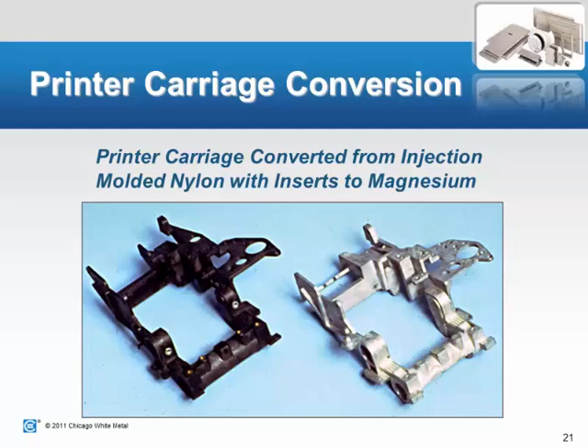This next component was a printer carriage component that started out as a plastic piece with some threaded inserts that were molded in. The customer indicated that the overall strength of the part was not exactly what they needed, but they didn't want to sacrifice very much weight in the overall product by converting to something. So magnesium was a great choice for this. It gave them the strength they need. The weight did not change that much. They could remove all the different brass and steel little inserts that you can see in the plastic part, and allowed a good cost saving as well there.